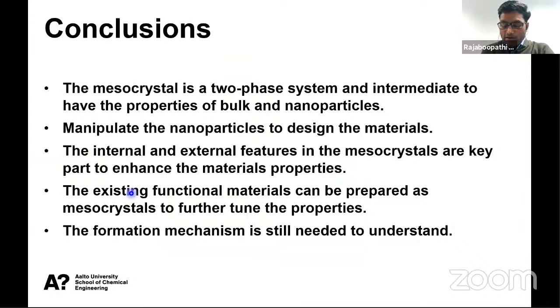So to conclude my talk, the mesocrystal is a two-phase system, and it is an intermediate having the properties of bulk and nanoparticle because the size is in microns. We can have some extra space to manipulate the nanoparticles to design a particular material using this mesocrystal strategy. The internal and external features, for example, voids or amorphous phase, highly faceted crystals, we can use this property to enhance the material property.